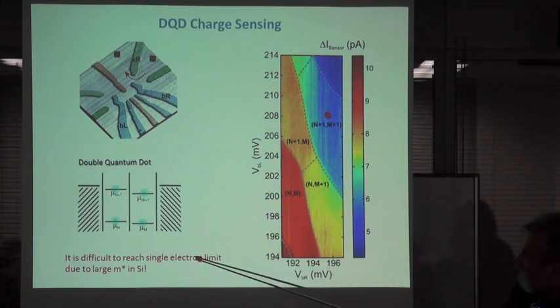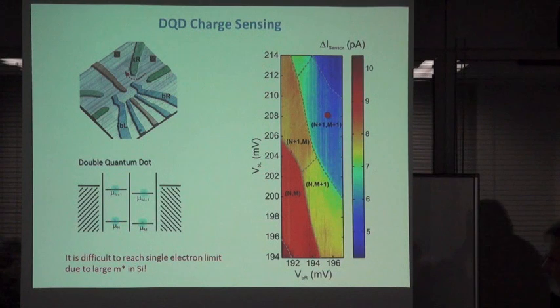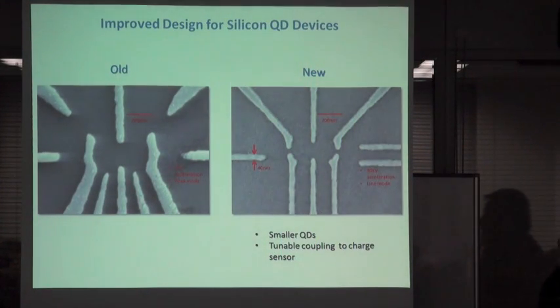However, in silicon germanium, it's quite difficult to reach the single electron limit due to the relatively large effective mass compared to gallium arsenide, for example. That's why we were not able to really get with this device to the single electron limit.